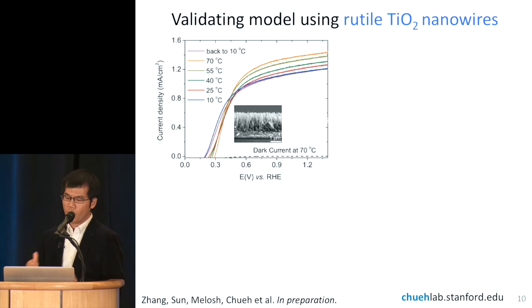So what we have done here is to make nanowires of titanium dioxide so we can control the diameters and the distances and the relative transport length more accurately. This is just one of those nanowires you can see in the cross-sectional image there. We're showing you again the improvement in the photocurrent as a function of temperature. The increase is okay, it's on the order of about 1% per Kelvin, so typical, comparable to the iron oxide case.